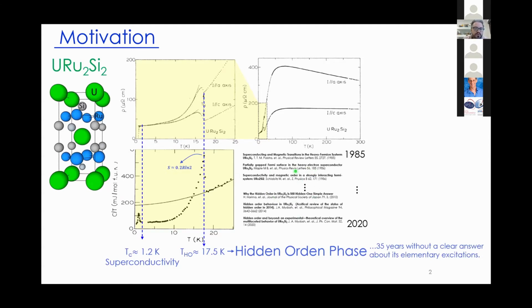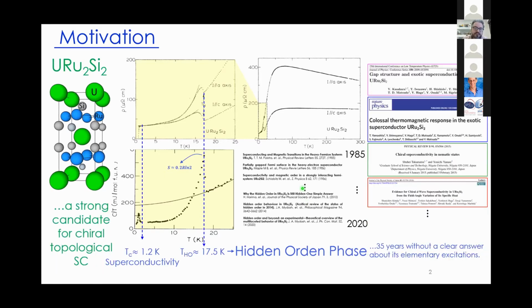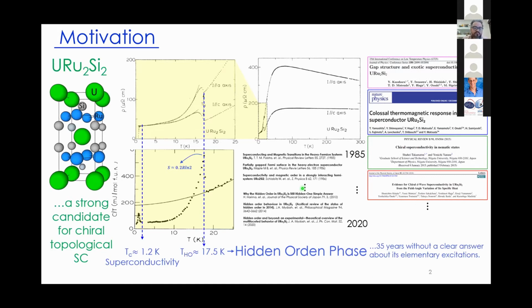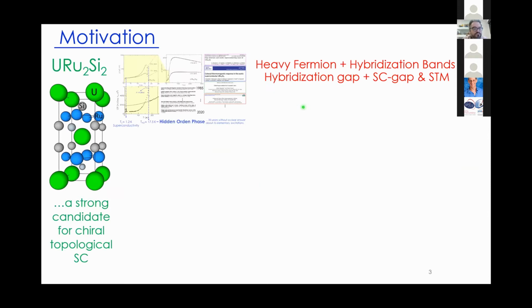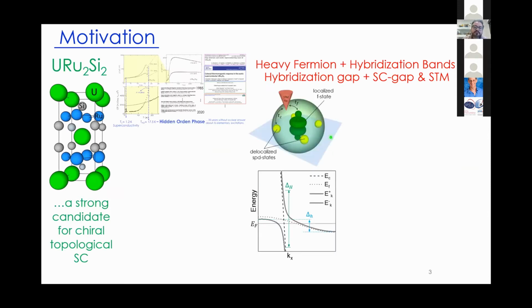A lot of experimental and theoretical work has focused on trying to understand this phase, but after 35 years we don't have a clear answer about the elementary excitations in this specific phase. And with respect to the superconducting phase, there are references that point to uranium-ruthenium-2 silicon-2 as a strong candidate for chiral superconductivity. So uranium-ruthenium-2 silicon-2 is part of the heavy fermion family of compounds.